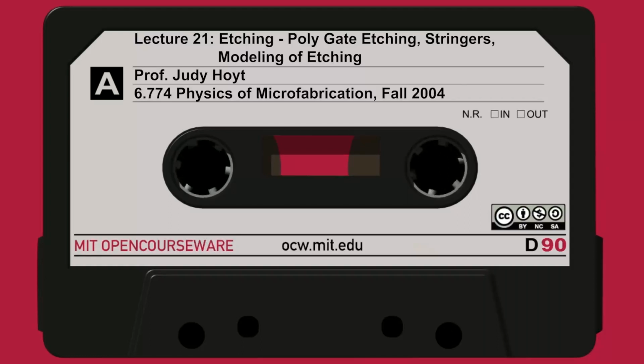So not only are we fully siliciding the gates, but sometimes we're actually replacing the polysilicon with another material, a metal gate material. And titanium nitride is a very popular one. So gate etching is evolving from not only having to etch poly and stop on dielectric, but now we may have to etch metals. So lots of new technologies have been developed over the last 2 or 3 years and will continue to be developed to push the technology forward.